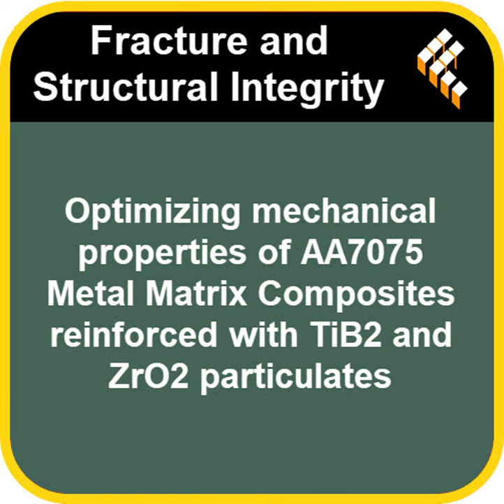Okay. But they also used that elemental analysis, EDS, on the worn surface, and they found oxygen. Oxygen. Hmm. From the air. Yes. The friction generates heat, and this heat can cause the exposed aluminum surface to react with oxygen in the environment, forming a thin, hard aluminum oxide layer. And that oxide layer protects it. It can act as a protective layer, sometimes called a self-lubricating oxide layer, further reducing wear. It's quite a complex interaction.